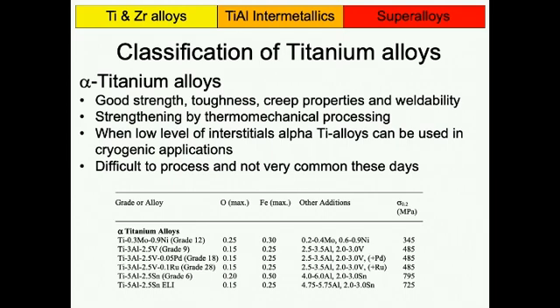All right. So you form new grains, and because they nucleate, they're small and then they start to grow. So that's a fundamental way of refining the microstructure, and that's the way you can strengthen alpha titanium alloys. And either you just keep the work in the material, or you do the heat treatment to recrystallize it. And of course, the problem when you have to hot roll or hot forge the material is that it can be quite tricky to actually retain the stored energy without getting too much recovery. Because when you get too much recovery, you don't store the energy, and you might struggle to recrystallize the material.